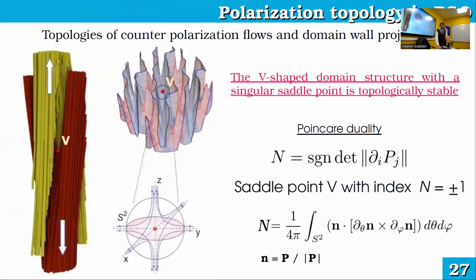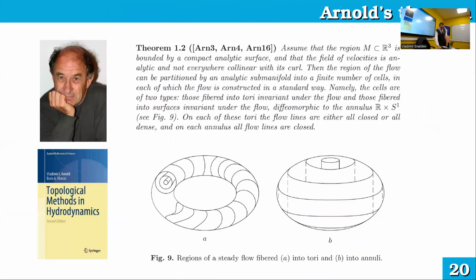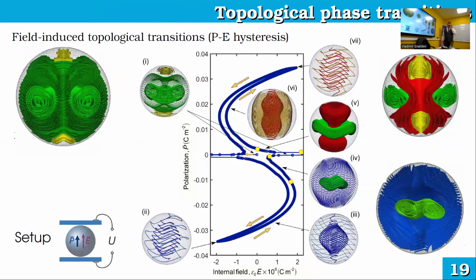In the case of nanoparticles, for example, something like this, you have a free boundary condition on the surface of the nanoparticle because it's embedded in some medium, and at the top and bottom of the medium you have, again, a Dirichlet boundary condition for potential to simulate application of an electrical field. So basically, very different boundary conditions depending on the scenario, depending on what we're doing.